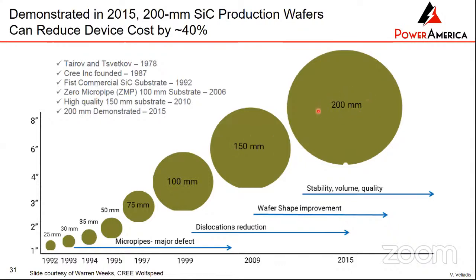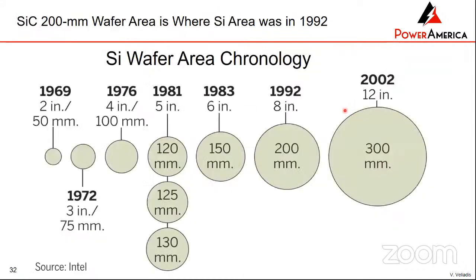And 200 millimeter wafers have been fabricated, but they're not in production. They're basically in the stage of research. Now, if you look at silicon, just for a comparison, silicon was making 8-inch wafers back in 1992, and 8-inch wafers for silicon carbide are expected over the next 2 to 3 years. So basically, silicon carbide wafers with respect to area are about 30 years behind compared to silicon.